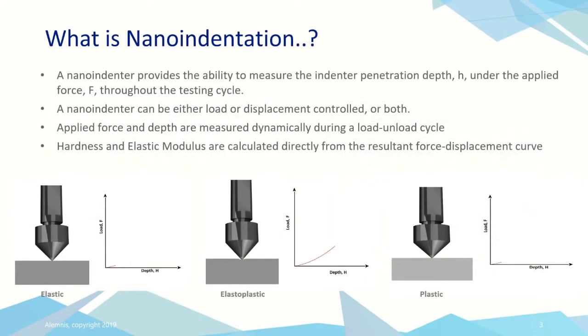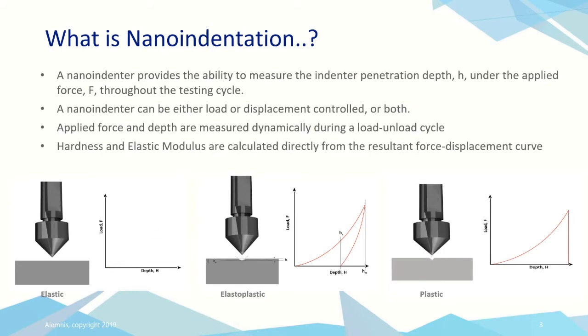Okay, so let's talk first a bit about nanoindentation. Nanoindentation is basically a continued development from macro and micro indentation. The problem was when conventional indentation techniques were developed, the indentation depth couldn't be reduced too much because the indent could then no longer be seen in an optical microscope. So instrumented indentation or nanoindentation was developed where we monitor load and depth in real time. And this gives us a load depth curve, which is like a fingerprint of the material.